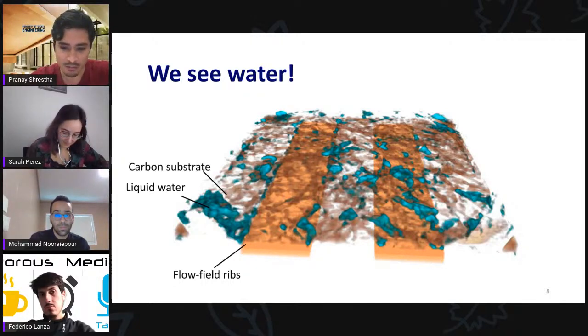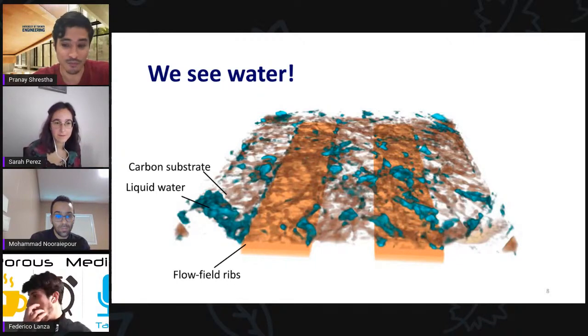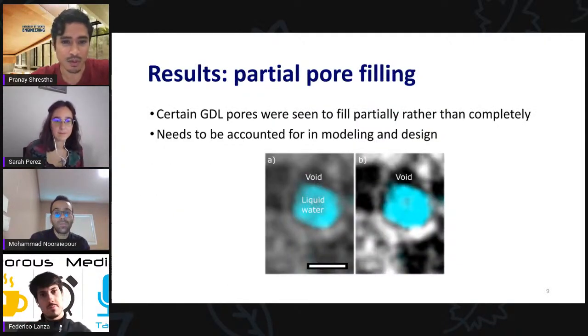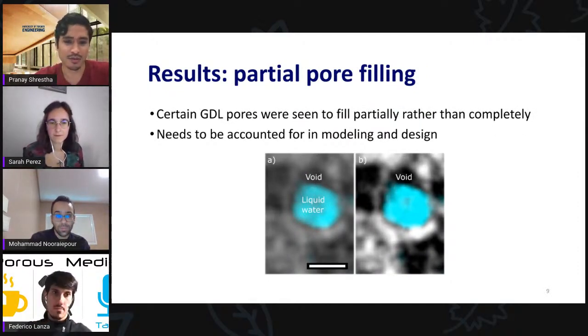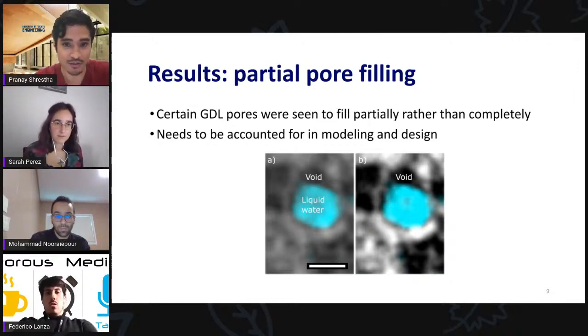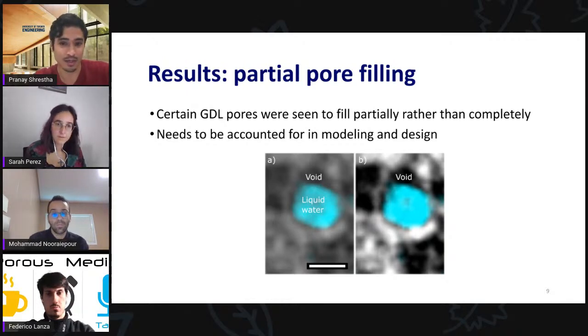And I would like to highlight some of the interesting findings from what we saw. I'll highlight a couple of key findings, where we found that certain pores in the porous layers, the GDL, which is short for gas diffusion layer, the porous medium of interest for us, were partially rather than completely filled. A lot of the modeling and design assumes fully filled pores.